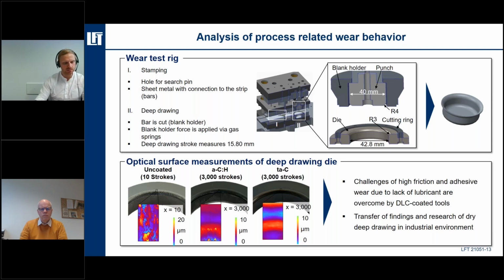The process basically consists of two steps: the stamping process and the following deep drawing. The cups, which you can see in the upper right corner, have a diameter of 40 millimeter and a depth of about 20 millimeter. The tool system thus enables us to do dry forming of 100 cups per minute and is used to investigate the tribological behavior for lubricant-free forming of drawing by using deep drawing tools.